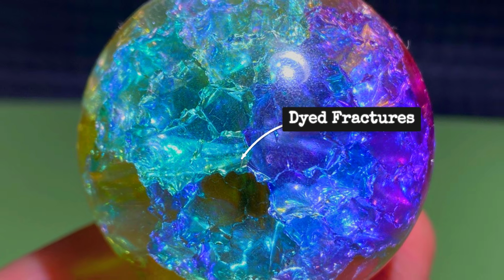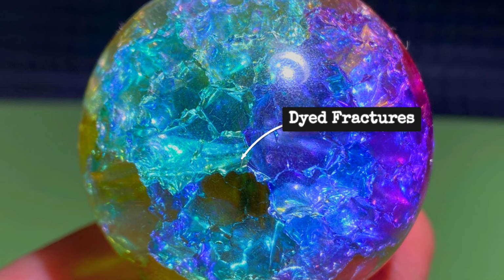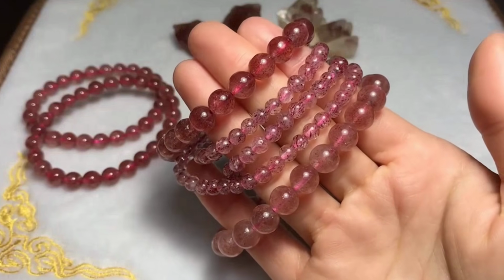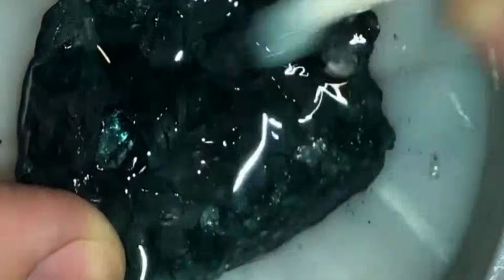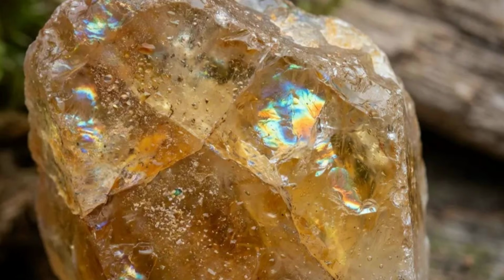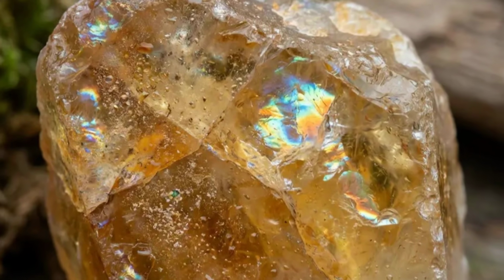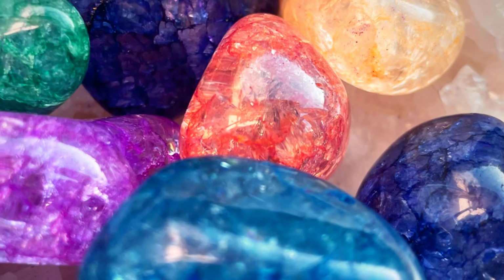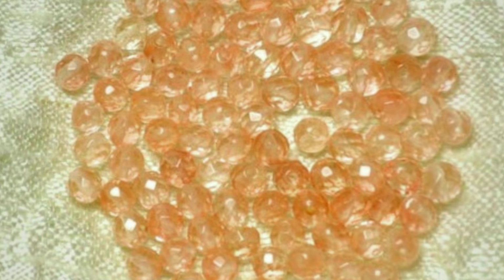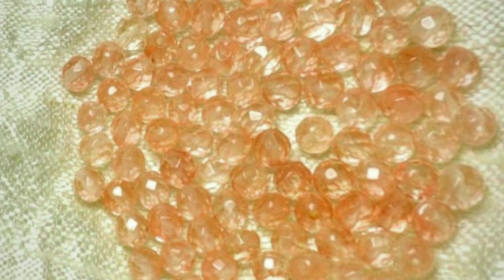Under a 10-power loupe, you will see dye concentrated in the fracture lines like ink pooling in the cracks of old concrete. Leave it in direct sunlight and the color fades. Rub it with acetone and the dye transfers to the swab. Retail price? $1 to $5 per carat. If you see a quartz with wild saturated color and a spiderweb of internal cracks, you are looking at a dyed fake that cost someone pennies to produce.